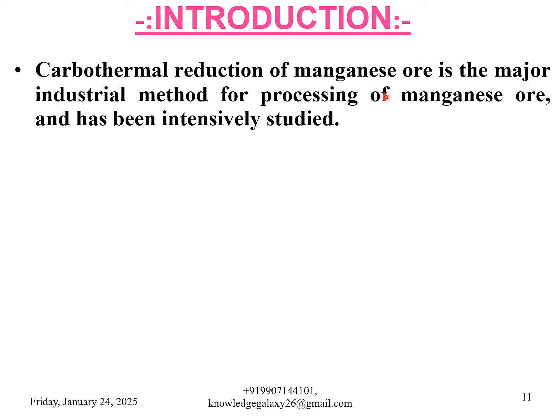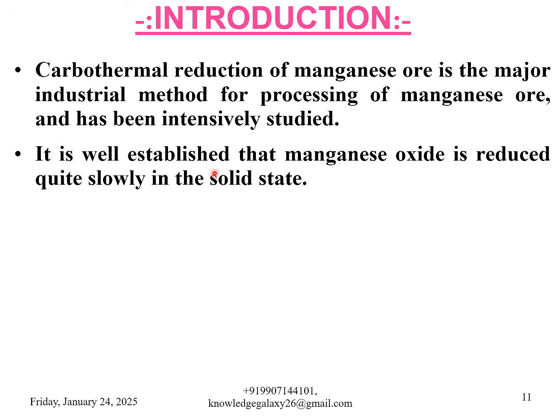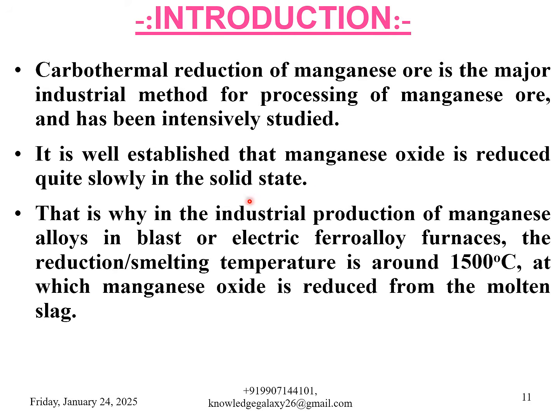Carbothermal reduction of manganese ore is the major industrial method for processing of manganese ore and has been intensively studied. It is well established that manganese oxide is reduced quite slowly in the solid state. That is why in the industrial production of manganese alloys, in blast or electric ferroalloy furnaces, the reduction or smelting temperature is around 1500 degrees Celsius, at which manganese oxide is reduced from the molten slag.